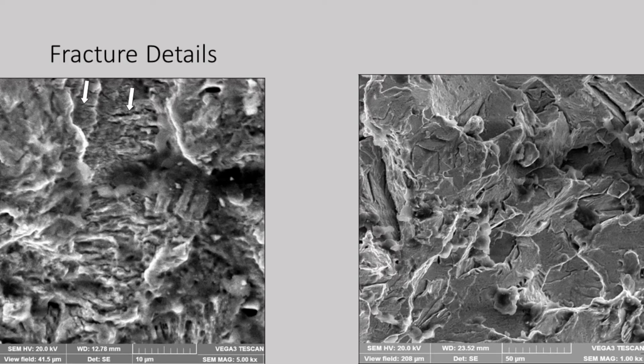And for steel, structural steels, they're not very well defined like some other metals. And you have to sometimes search for fatigue crack striations if you're trying to determine if that's the cause. And this next picture is at about 1,000 magnification, and this is the portion of the fracture surface where we had brittle fracture. This is what you see here is called cleavage cracks.